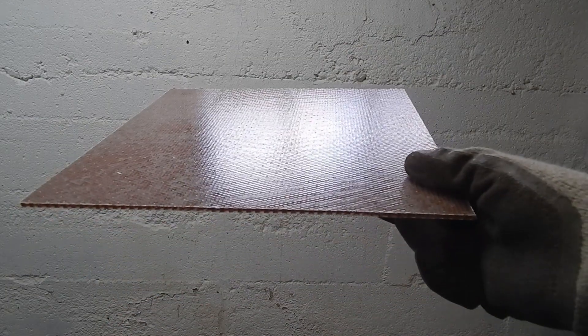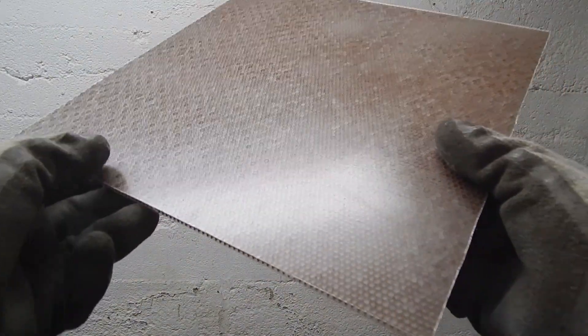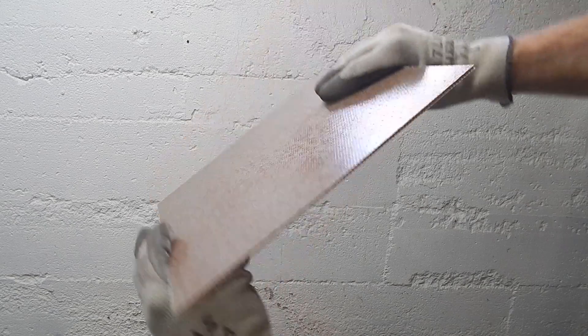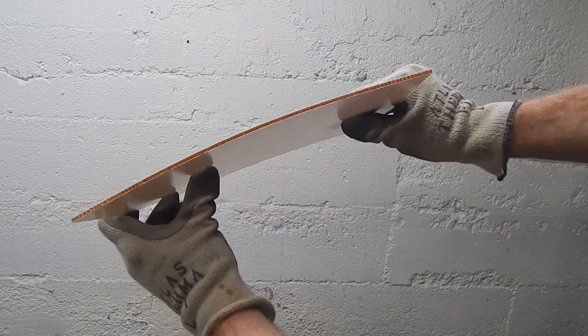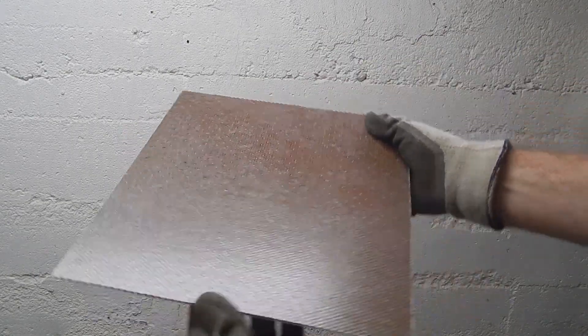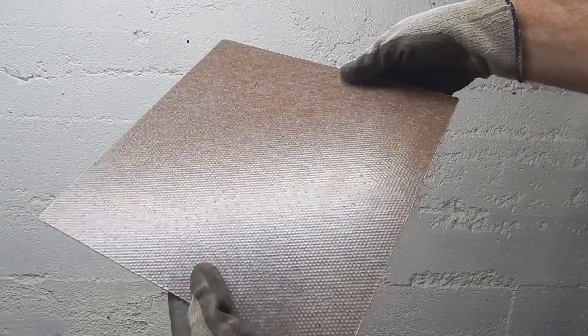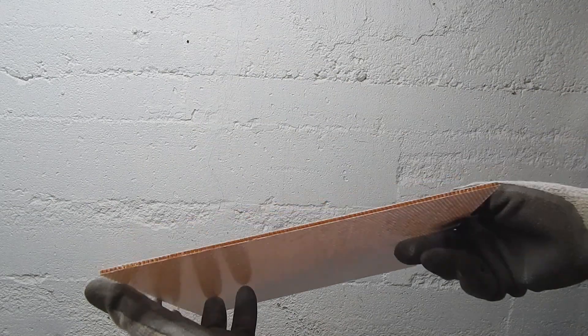Having a look at the finished panel. There's some variability in the amount of resin and what looks like little bubbles of resin on the honeycomb cells. I'm not sure what's going on there. I'm sure there is excess resin here or resin that should have stayed in the panel. The mold side surface looks really good. There are a few very light pinholes in it. But it's pretty decent given how little resin and little fiber there is there. And stiffness wise it's not very beefy. But it's better than you'd imagine it would be given how light it is. And of all the samples this is so far the lightest by a pretty good margin.